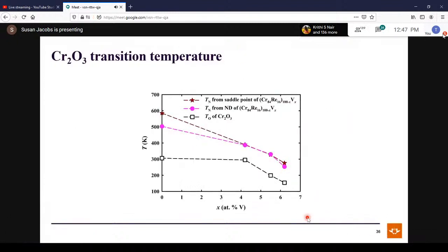Okay, so if we have a phase diagram of the alloy as well as the oxide, the red or brown stars are transition temperatures from the saddle point. The pink circles are from neutron diffraction. There's fairly good correspondence for the mother alloy and good correspondence for the other alloys. And also for the oxide temperature, here again we see that as vanadium concentration increases, the Tn of the oxide decreases. So once again, we want to suggest that it's not just Cr2O3, but rather a vanadium-doped Cr2O3.